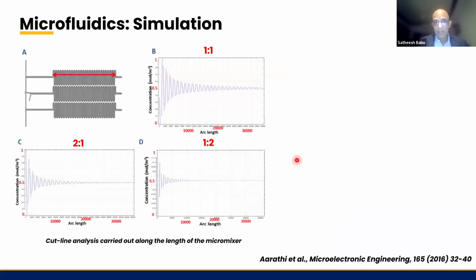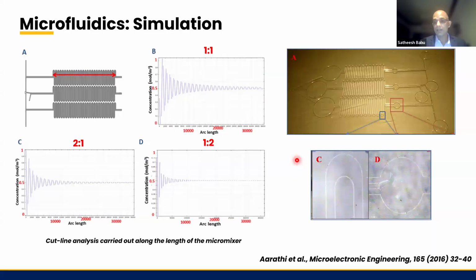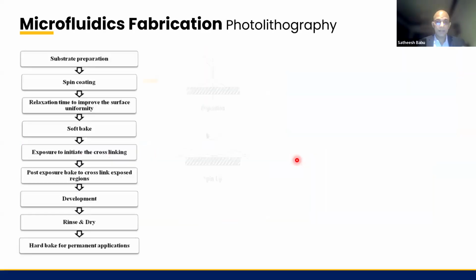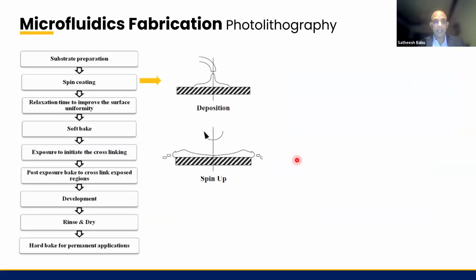So here we started the microfluidics with the COMSOL simulations, and then we developed the microfluidic systems, with meander type channels with alternately varying diameter. And we fabricated the optimized design by using photolithography, followed by soft lithography for the stamp. Briefly, this is how we have done it.